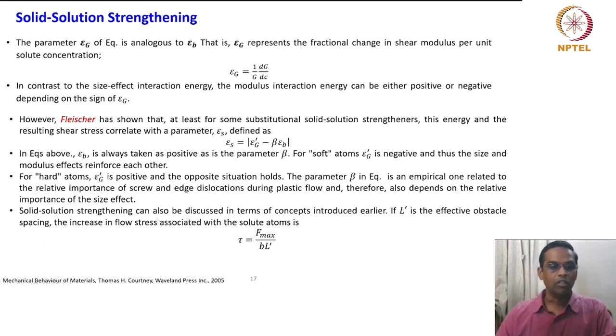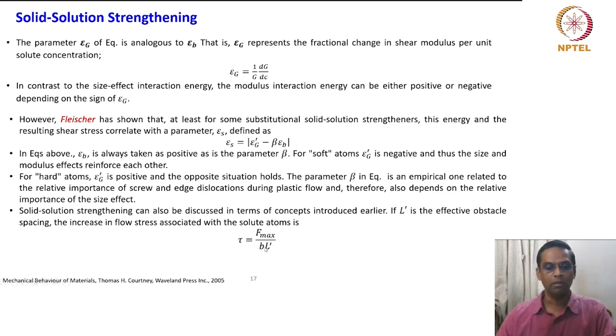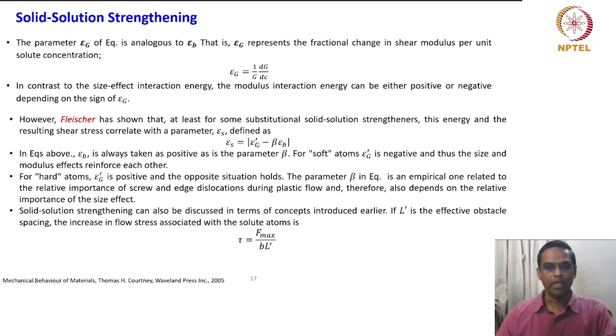Solid solution strengthening can also be discussed in terms of concepts introduced earlier. If L_prime is the effective obstacle spacing, the increase in the flow stress associated with the solute atoms is tau equals F_max divided by B times L_prime. This is a very general and generic expression. The semi-quantitative expressions shown here represent one way of looking at it, and another way is to keep this basic equation and address the problem in a similar manner.